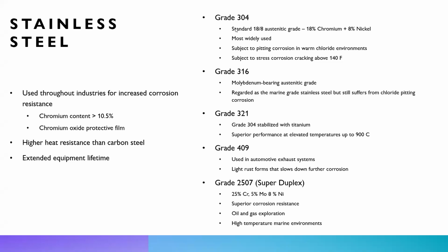Grade 409, which was interesting looking it up, is used in your automotive exhaust systems. So it's really good versus off gases, atmospheric off gases, corrosion. It actually forms a light rust that slows down the corrosion, but doesn't have that fancy appearance that you want with your stainless steel. Finally, another grade is going to be your super duplex. Grade 2507 is part of that super duplex family, which has all the additives that make it some of the more superior corrosion resistant applications. So in your really critical applications like oil and gas exploration, you might have to go with your super duplex to avoid any corrosion issues down the line.